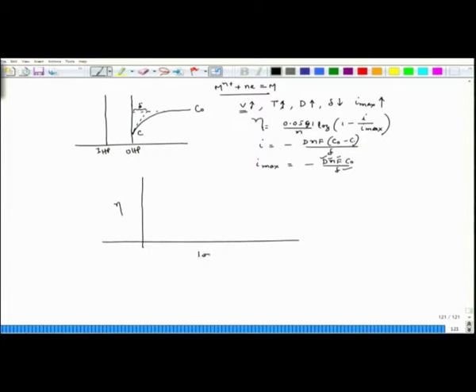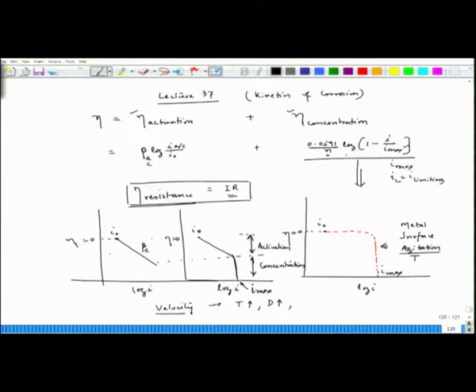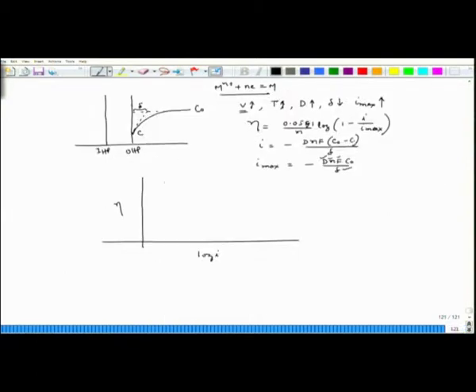Now, interestingly, if I max increases, then I would have a corresponding change in the polarization response. You could see the combination of those two situations, one is activation and another one is concentration. First it will go like this, which is the activation part, and then the concentration part would increase this particular polarization, which is cathodic side. This is I0 corresponding to eta equal to 0. Now, as I max is increasing, that suggests that I max would go to the right direction. So now I max would appear at a new position. If this is my I max, then this activation polarization would still extend till I max is reached in the second case.